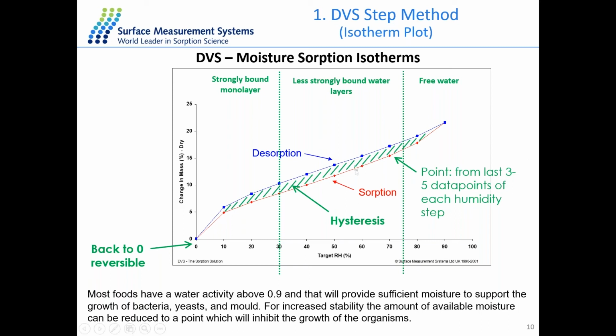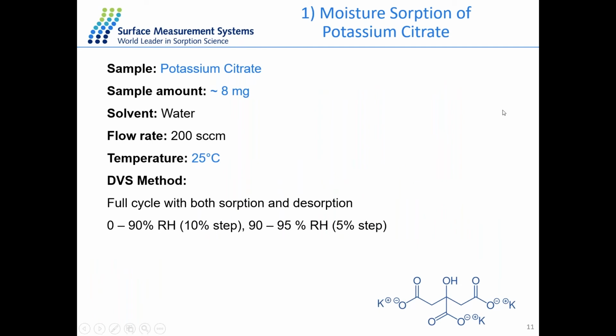And this isotherm is a quite typical type 2 isotherm, which indicates it's beginning with a monolayer region, and then the multiple layer region with loosely bound water, and then at higher humidity has the free water. And the monolayer region is a very stable state, and that could be related to the stability of the pharmaceutical ingredients. And for the step method, the first example I'd like to show you is about the potassium citrate.